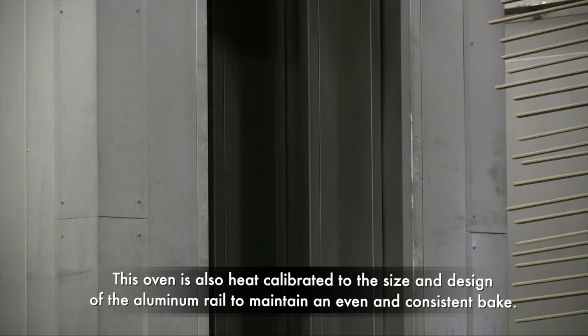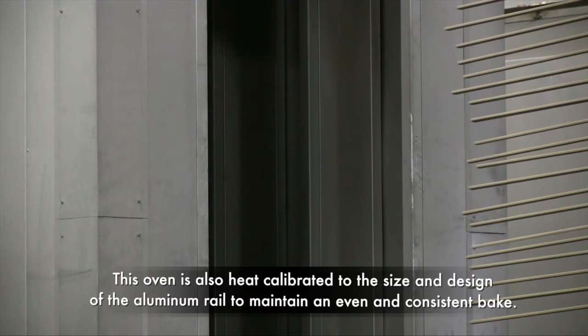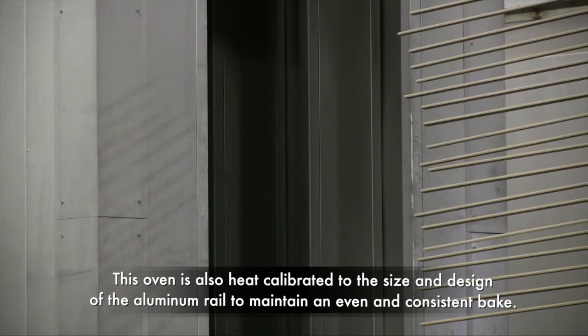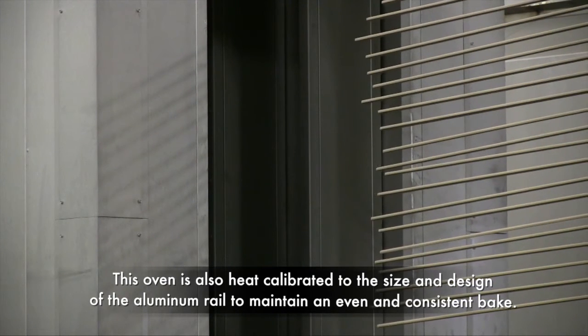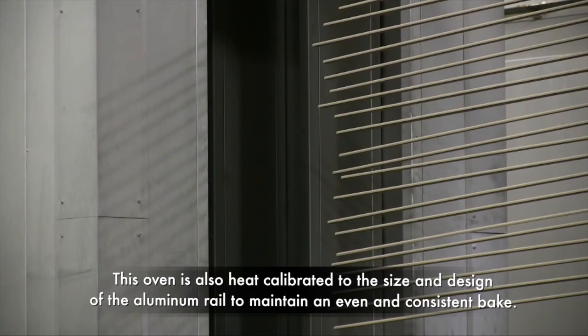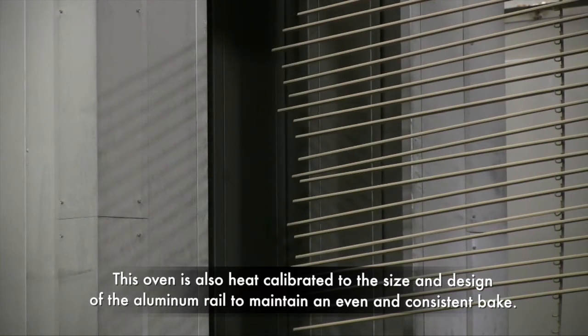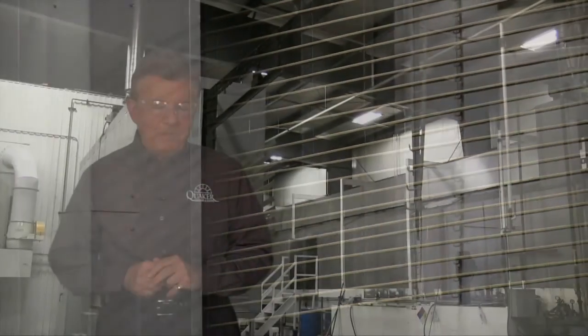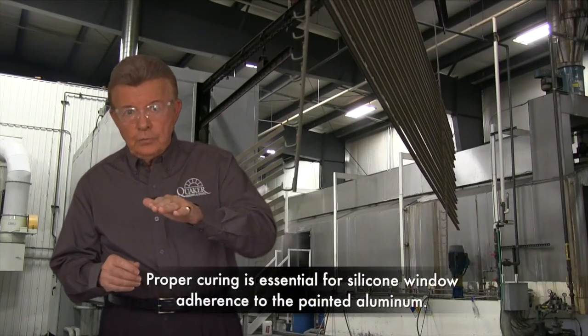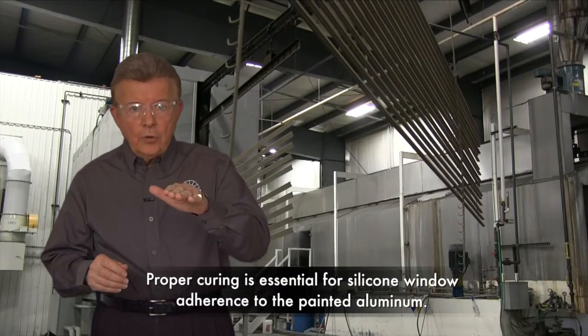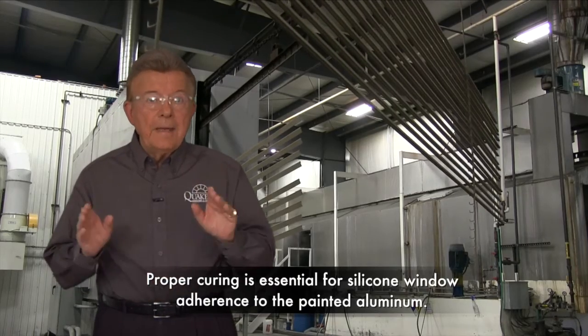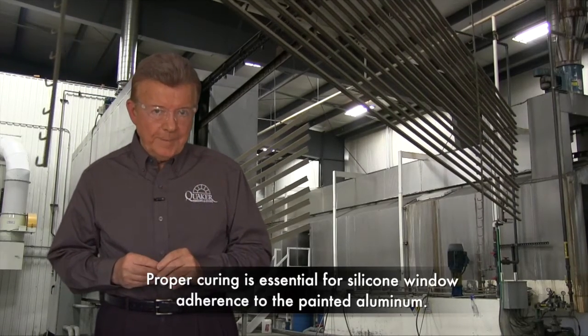Next, the rails travel into a computer-controlled convection oven to complete the curing process. This oven is also heat calibrated to the size and design of the aluminum rail and uses air to circulate around the substrate to maintain an even and consistent bake. It's here that the gel cures to create a hard coat finish that bonds with the aluminum. This process is essential because if the paint is overcured or undercured, then silicone used to seal the window may not adhere properly to the painted aluminum.